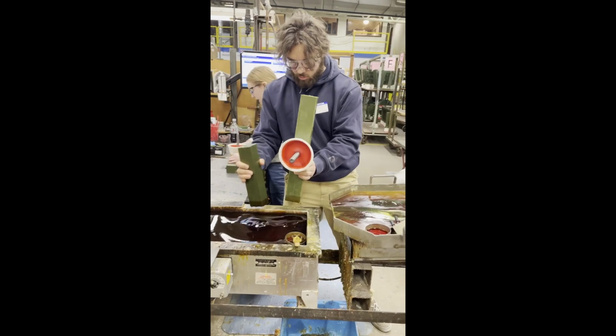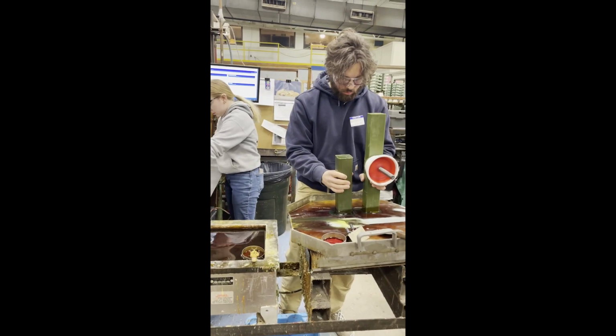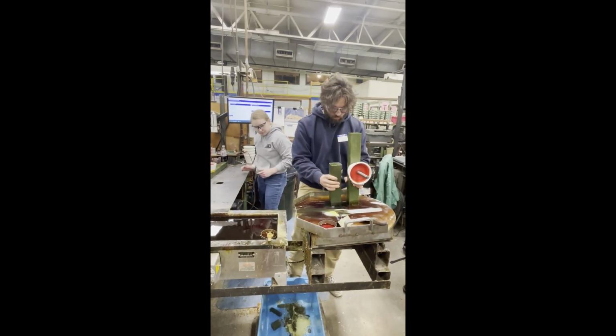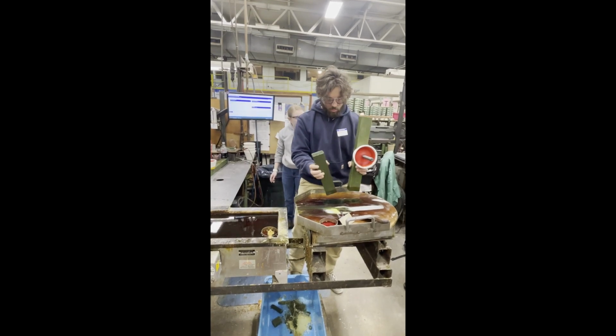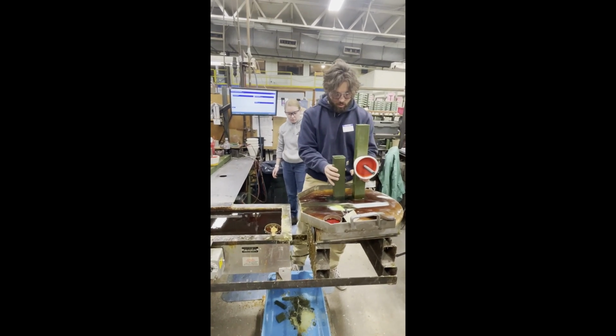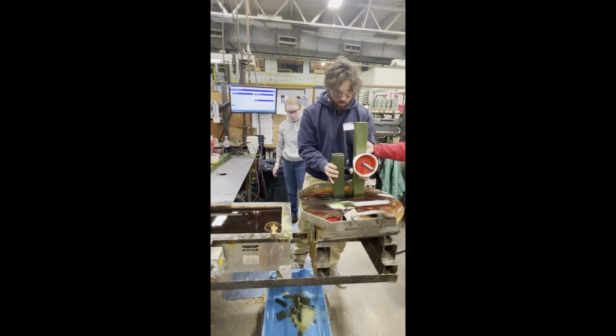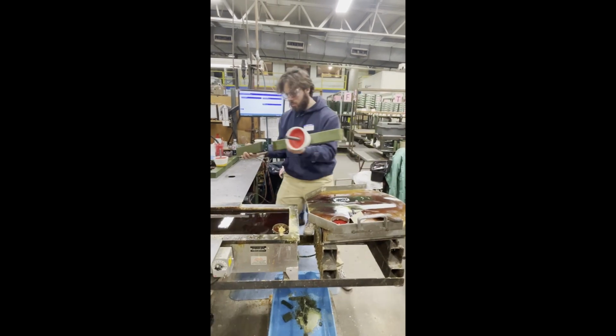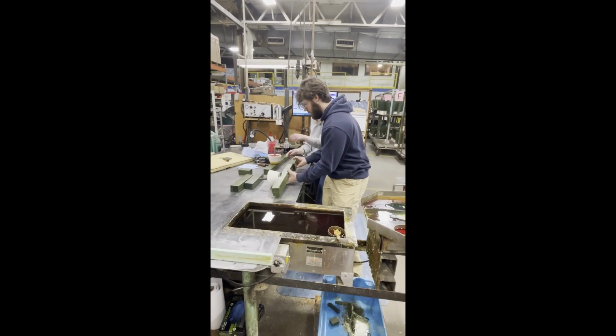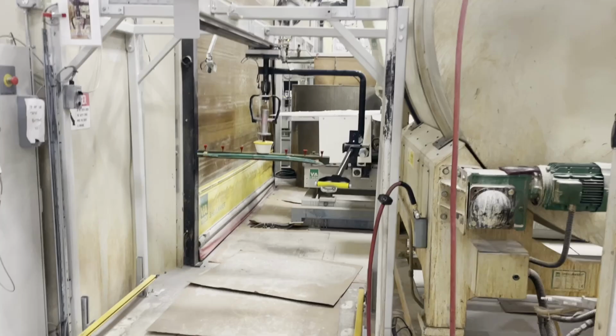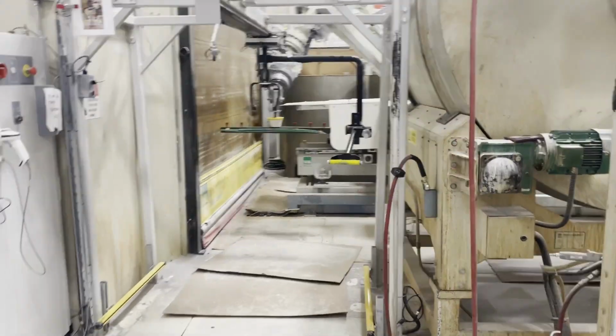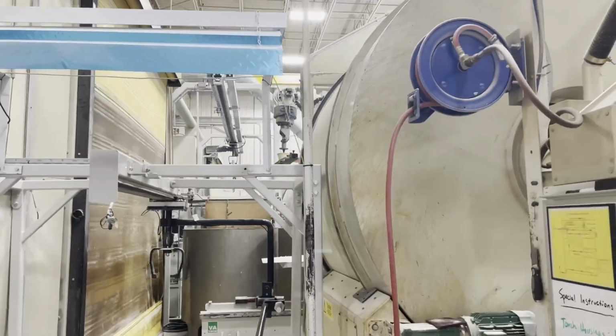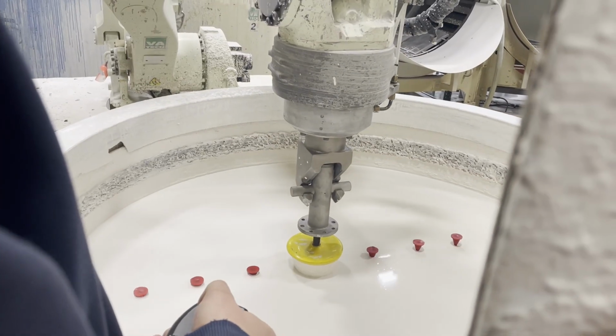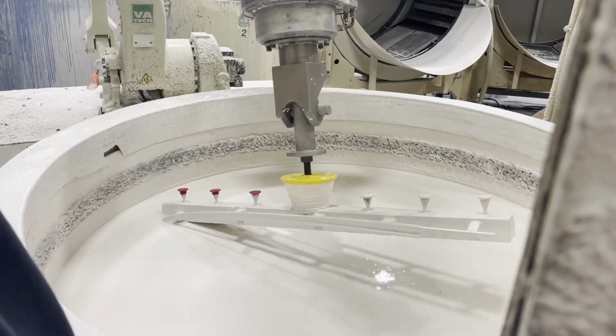This process began by 3D printing 4 sword blades. They were printed out of pure PLA, and each blade was printed in 4 separate pieces, which were then glued together. And then the 3D printed swords were attached to a wax gating system. That gating system was coated in multiple coats of a ceramic slurry, and then the wax and PLA were burned out to create the mold. And then during casting, the metal is just poured in.